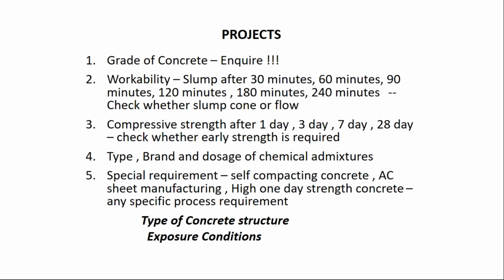Because this kind of workability or slump retention cannot be obtained unless we use chemical admixtures at site. One of the key requirements is that the cement has to be compatible with the admixture, and the admixture has to be compatible with the cement, both have to match each other, and the cement has to be mostly from one source, so that you get that compatibility constant throughout the project. And even if the cement and all materials are from the same source, what is important is that trials have to take place on a daily basis. That is what some of the projects where the quality control is very stringent do, so that there are no surprises at all.